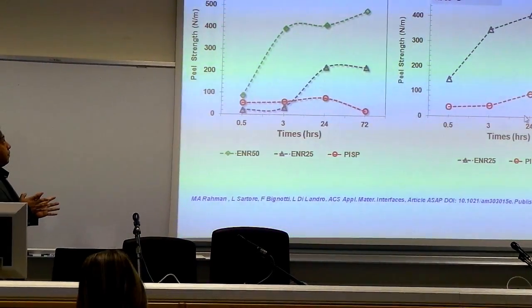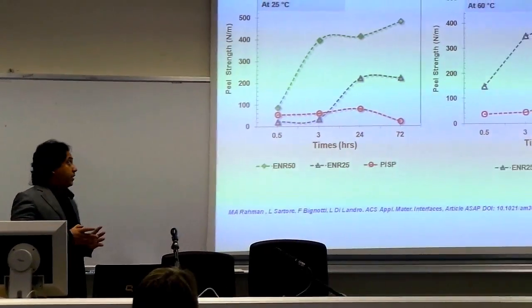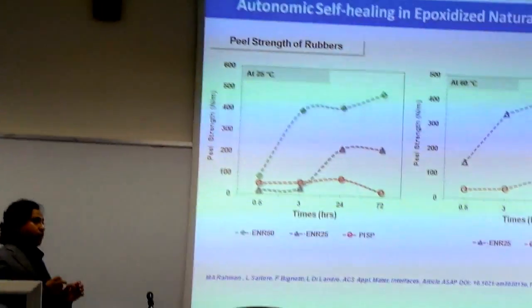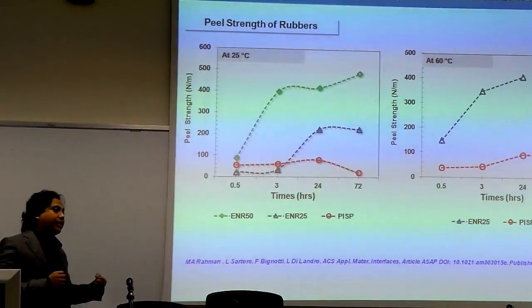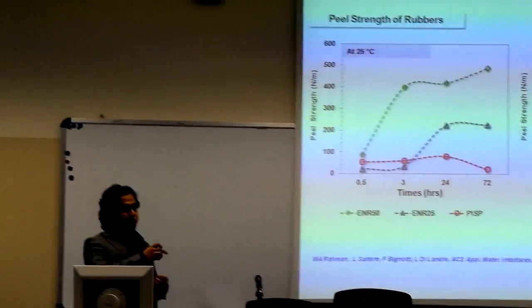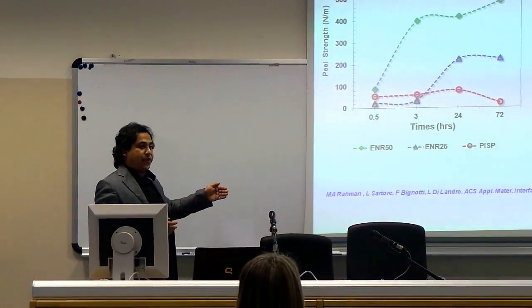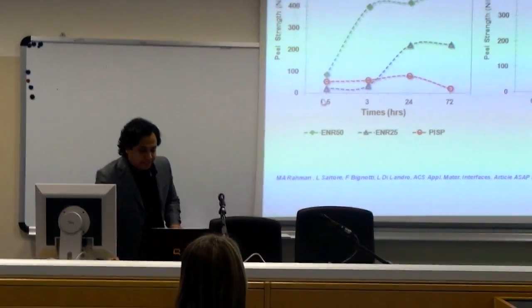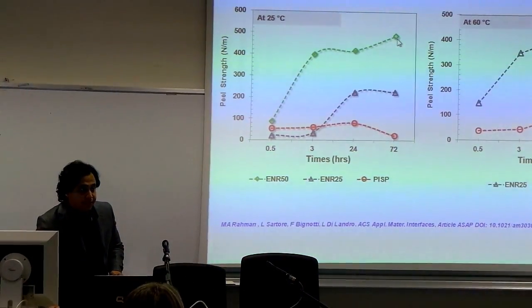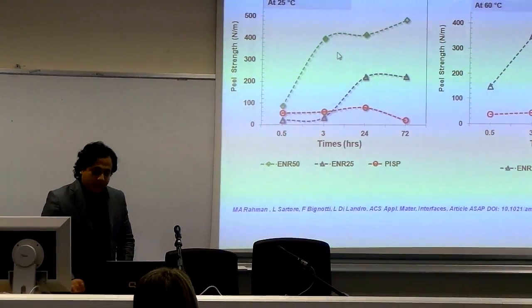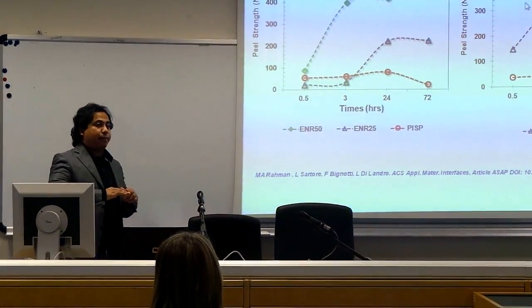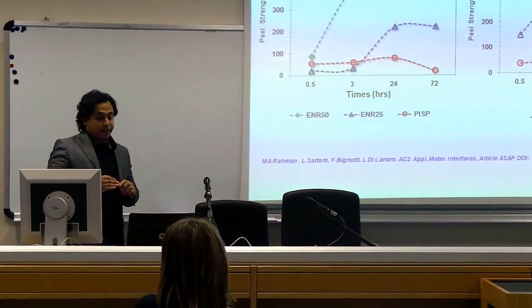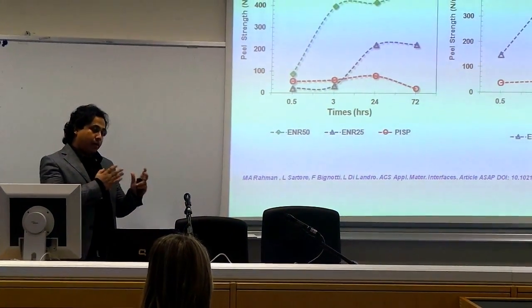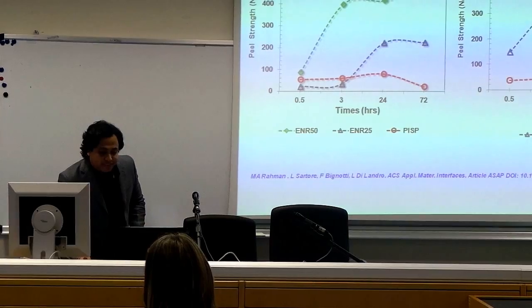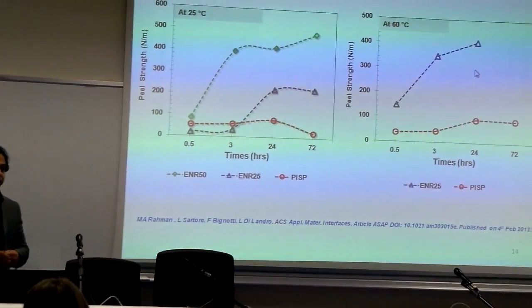Well, this slide presents the peel strength of rubbers. I should mention here that peel specimens were treated at two different temperatures, at 25 degrees Celsius and at 60 degrees Celsius for different periods of time. So the peel strength reported here is a function of time and temperature. As you can see, at 25 degrees Celsius, the highest peel strength was exhibited by ENR 50. And when I treated the sample at 60 degrees Celsius, the material showed higher peel strength than the material treated at 25 degrees Celsius. And you can see that the peel strength of ENR 50 is absent here.